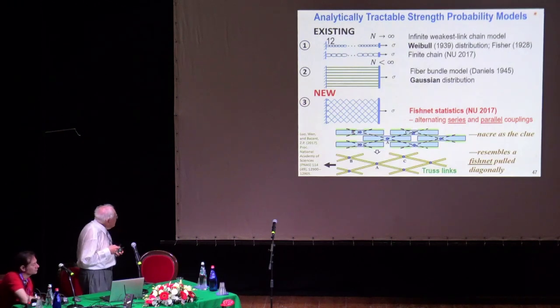Now another aspect. I mentioned there existed until 2017 only two models: the weakest link chain, where if one element fails, the whole thing fails, which must be finite as shown here in most cases, and the fiber bundle, this result of Daniel, which gives exactly that distribution. We found out that another system, which is actually modeling nacre behavior, also can be solved analytically exactly